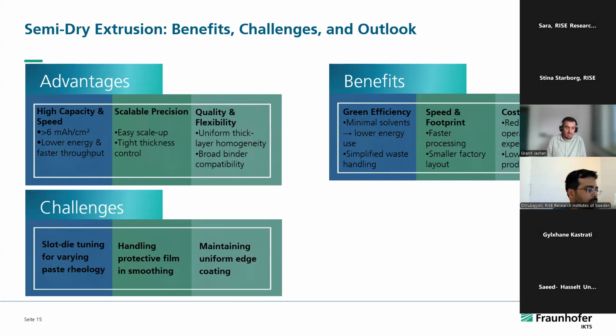The challenges, of course: for each kind of chemistry, the slot die still needs to be tuned, due to the differences in paste rheology, since different chemistry and different binder also have different behavior in terms of viscosity. That's why the slot die needs to be verified, and its geometry checked, to see if it's compatible with the material that is going to be extruded. Handling of the protective film in the smoothing process, as I mentioned, is a step that needs a lot of optimization. But as I mentioned, we are going forward on that topic, and soon we will have another way to handle that.